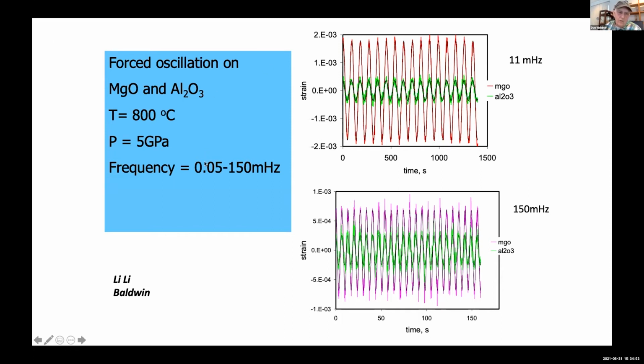In particular, we can go to frequencies a little over 100 millihertz. That's pumping oil through all the lines and so forth. That's, I think, what limits our high frequency end. But so if we look at a period of 10 seconds, maybe a little smaller than 10 seconds. And we've done experiments with low frequencies where the period is like 5 hours. That's been the longest we've tried. In this particular example, we're just looking at the images, and as in the previous slide, using corundum as a reference and MgO as the sample.